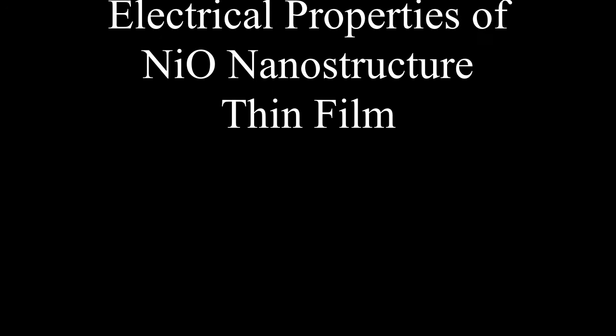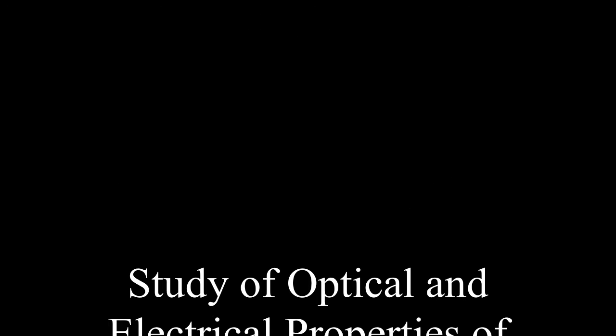Study of optical and electrical properties of NiO nanostructure thin film. Nickel oxide, NiO, thin films were prepared using a simple spray pyrolysis technique from hydrated nickel chloride salt. Solution, NiCl2·6H2O, deposited on glass substrates at a temperature of 450 °C, and with different solution concentrations,